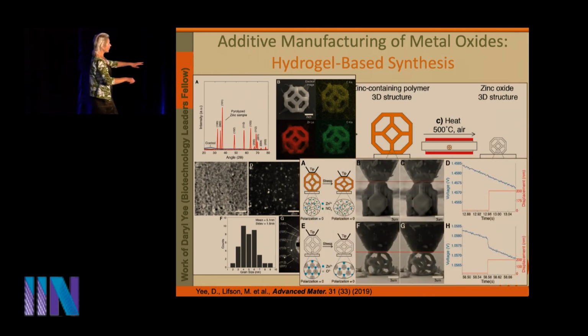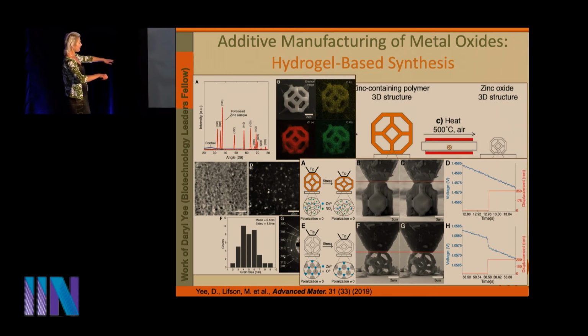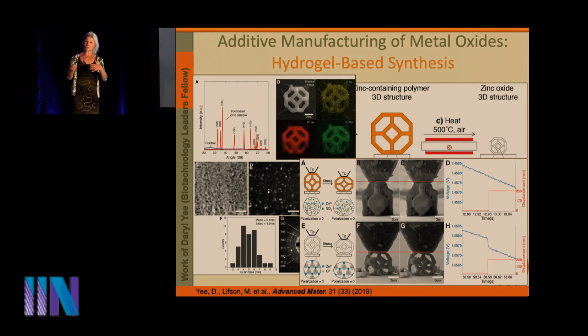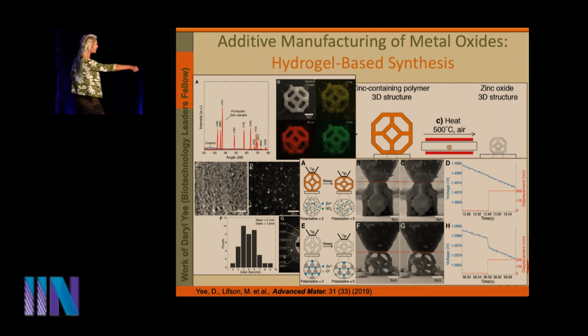Well, all right, so look at the first top part here. So this is the resin, the zinc oxide containing resin. Of course, it shouldn't have a piezoelectric response. Now, in our instrument, I showed you that we have the capability to assess the electrical response of materials in addition to the mechanical. So that lends itself very well to piezoelectric type experiments. So what you see here is the blue signal is the voltage, and the orange signal here is the displacement. So what we're doing is we're coming in contact with the structure, and then we displace it by something like 350 nanometers here in a step function. And what happens to the voltage? Absolutely nothing. No response from the resin, as we would expect.